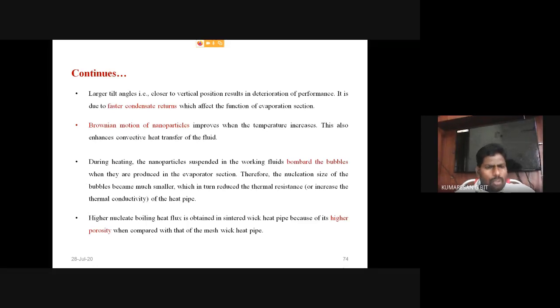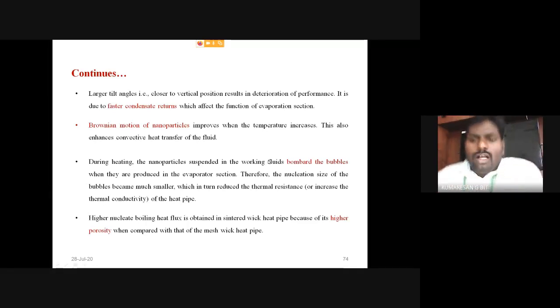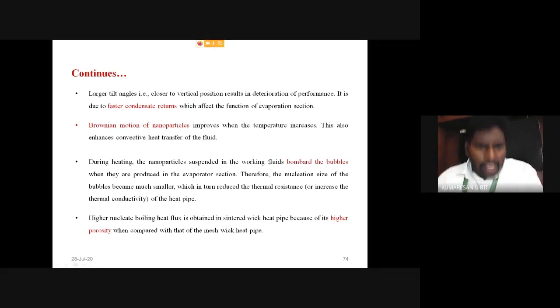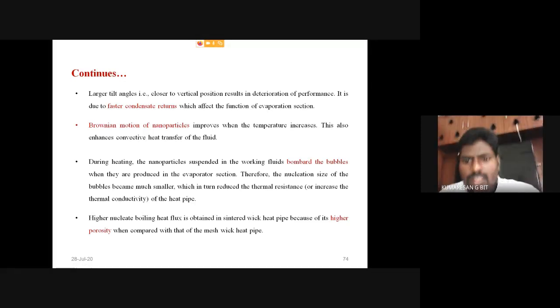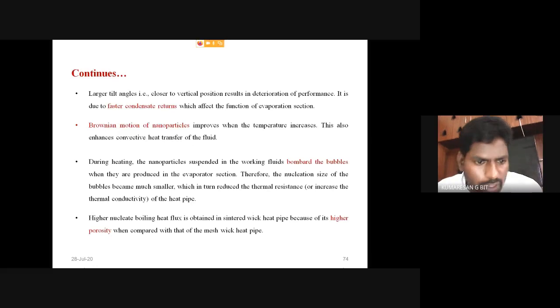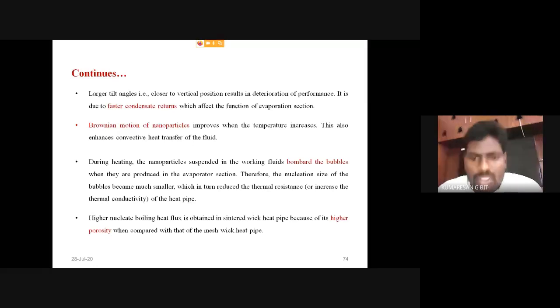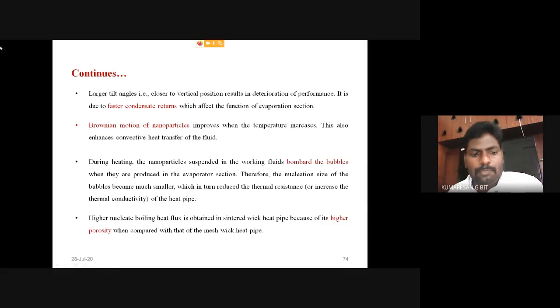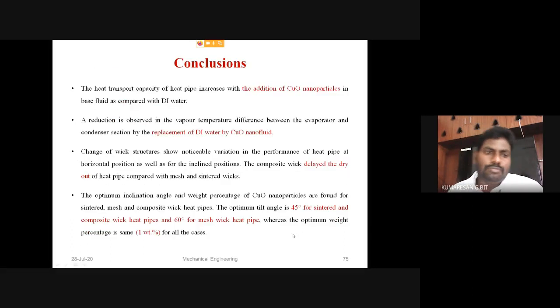Okay. And during the heating process, the nanoparticles suspended in the working fluid bombard the bubbles when they are produced in the evaporator section. Therefore, the nucleation size of the bubbles becomes much smaller, which in turn reduces the thermal resistance of the heat pipe. Then higher nucleate site formation is obtained in the sintered wick heat pipe because of its high porosity when compared with that of the mesh wick heat pipe.